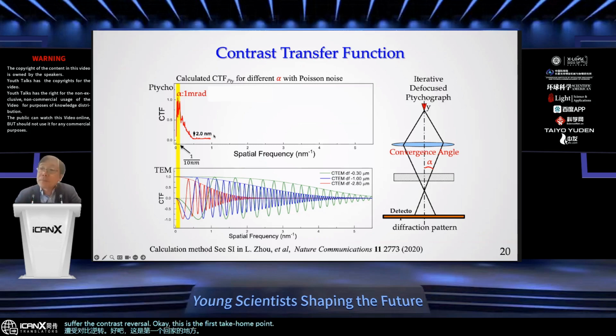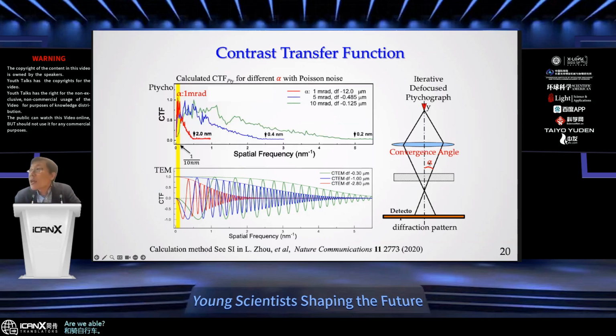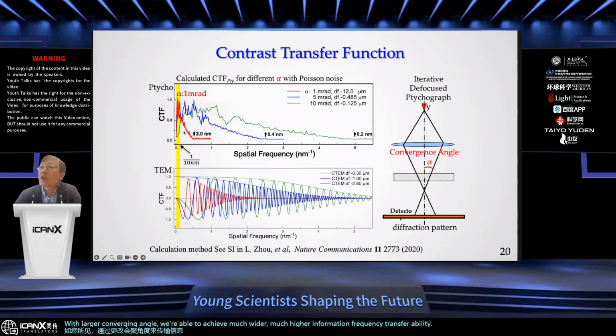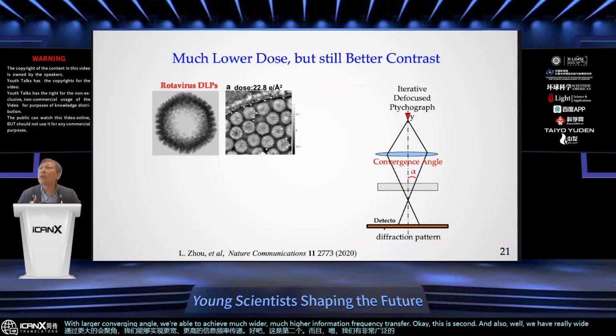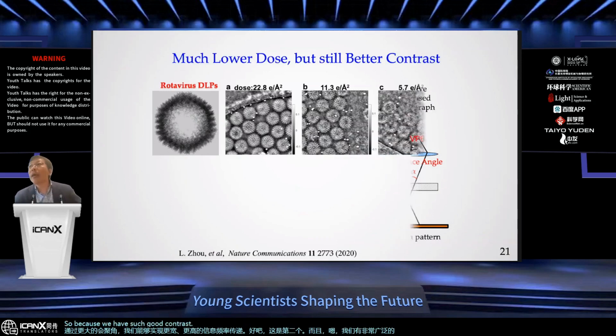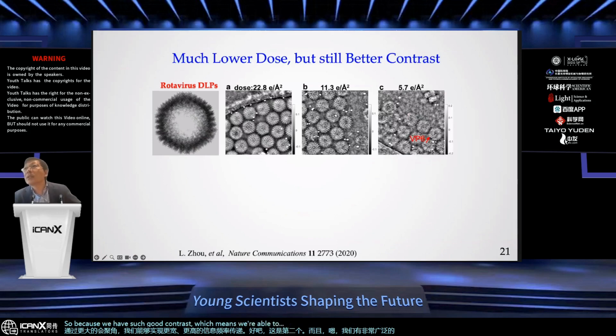And secondly, we are able to change the bandwidth of the information transfer by changing the convergence angle. As you can see here, with a larger convergence angle, we're able to achieve a much higher information frequency transfer. Okay, this is second. And also, we have a really wide information transfer bandwidth. So because we have such good contrast, we're able to continue decreasing the dose from 20 electrons per angstrom squared to 5 electrons per angstrom squared.